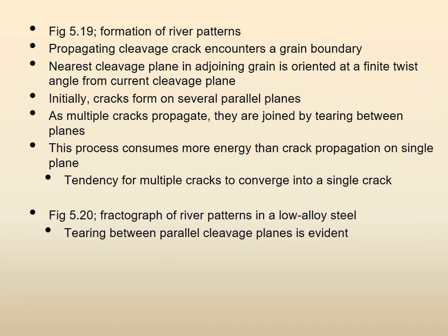We will see on the next page in the figure more details of formation of river patterns. A propagating cleavage crack, propagating means which is growing, which is moving, encounters a grain boundary. The nearest cleavage plane in the adjoining grain is oriented at a finite twist angle from the current cleavage plane. You see, there is one grain in which the cleavage is progressing.